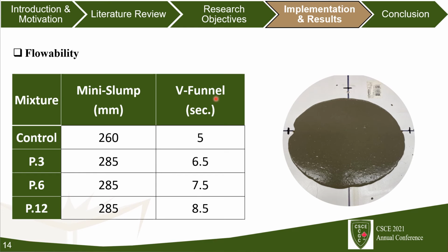As you can see in this table, in general, the viscosity was enhanced by increasing the percentage of the phase change material. For instance, for the P.12 mixture, the viscosity increased by 70% when the phase change material percentage increased from 0 up to 12%.